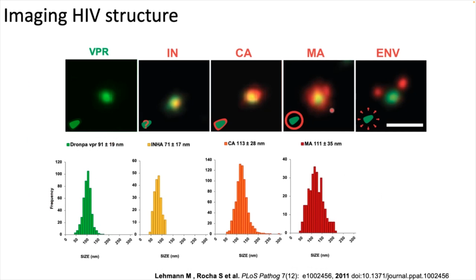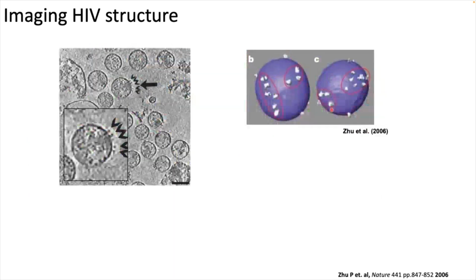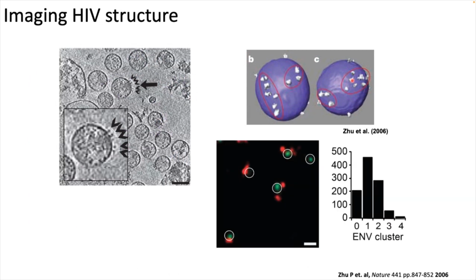But then we start getting these Mickey Mouse kind of structures, and we were like, what is this? Something wrong with antibody labeling? But then we look back into literature and into some EM images, and actually it seems that these envelope proteins form clusters on the surface of the HIV particles, and that's what we were seeing when we were imaging the viral particles. You had this, I'll say it again, Mickey Mouse. So these dots around the virus particle and the number of envelope clusters were actually in good correlation with the electron microscopy. And this was just a very basic study that we did back in 2008 or something.